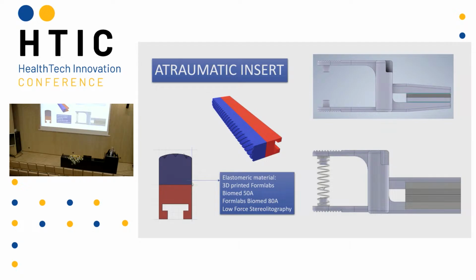And the upper layer is built of elastomeric material. The elastomeric resin was used for 3D printing in the technology of low force stereolithography. We used commercially available materials, Formlabs Biomed 50A and Formlabs Biomed 80A, with two different shore hardnesses. And as you can see, the insert also has serration. We developed the serration on the surface of the inserts just to avoid slipping of the instruments from the vessel.